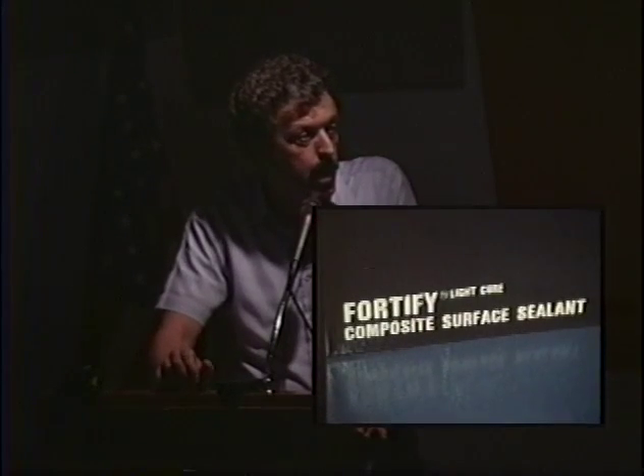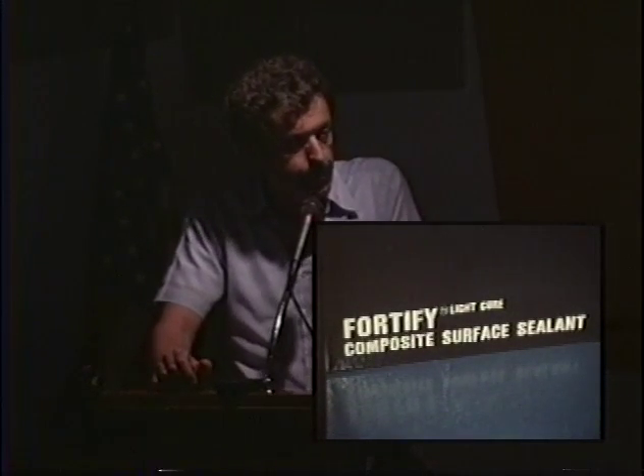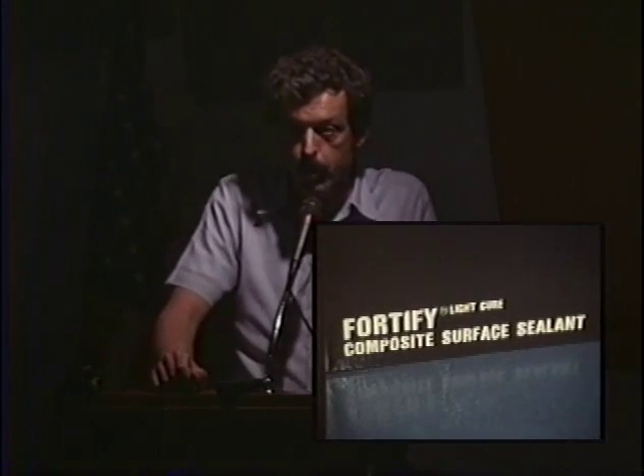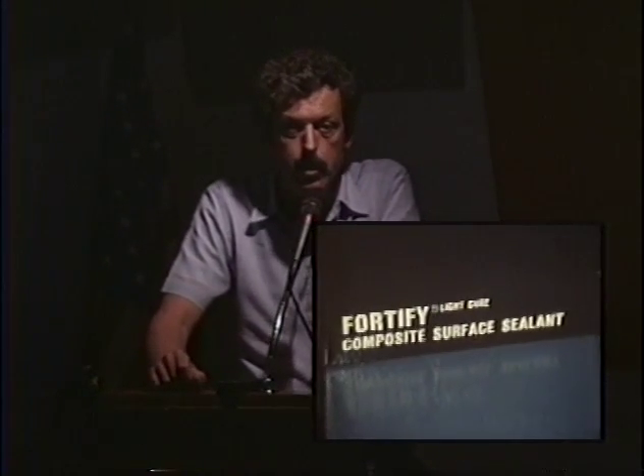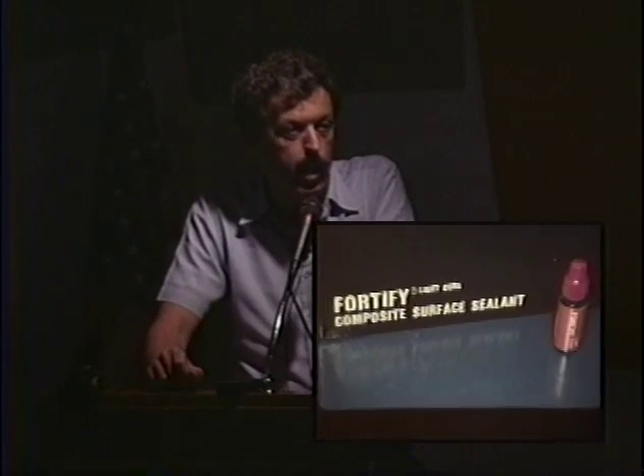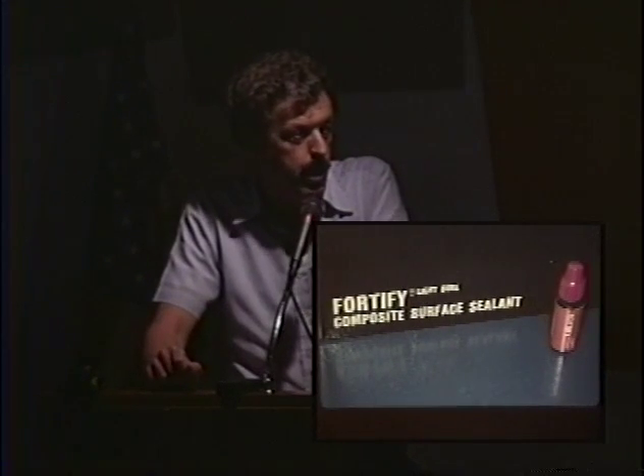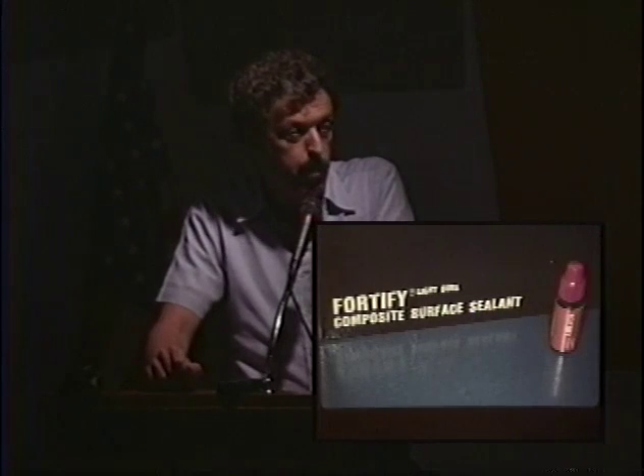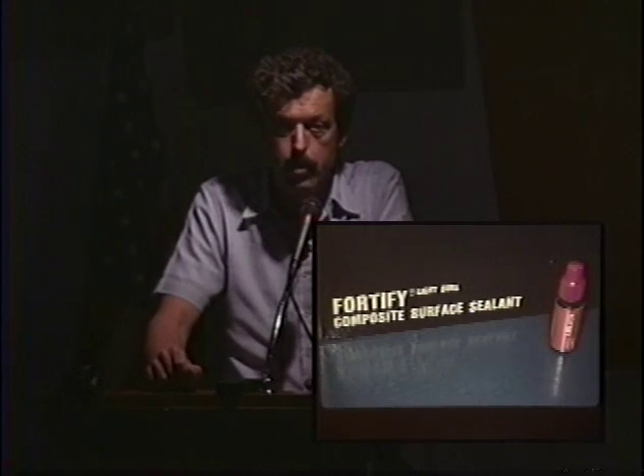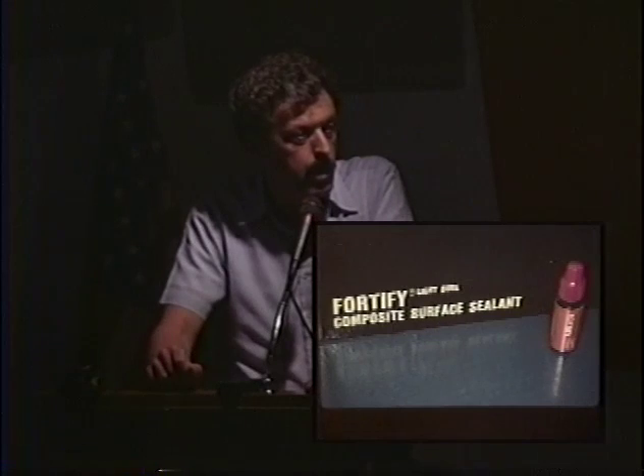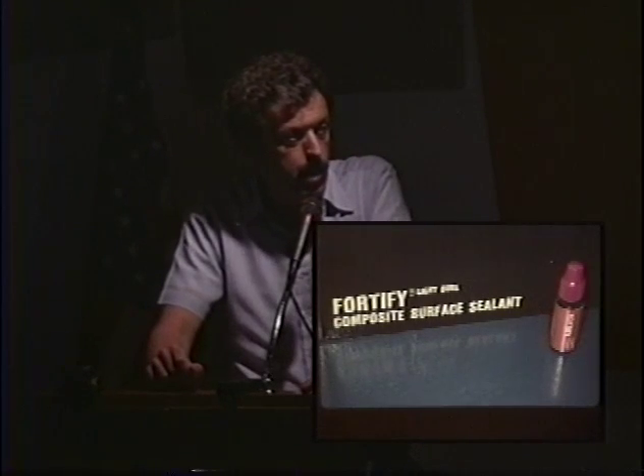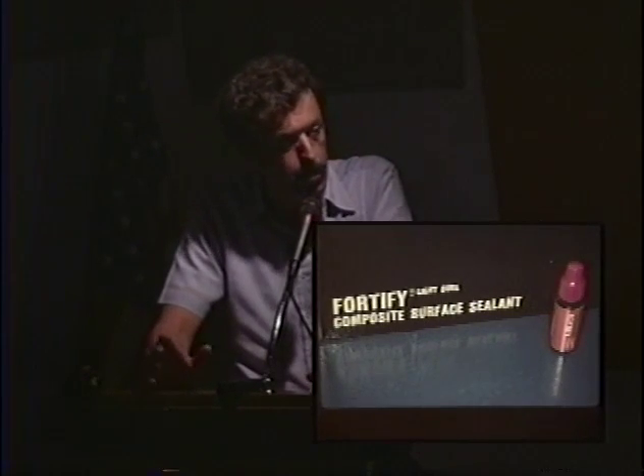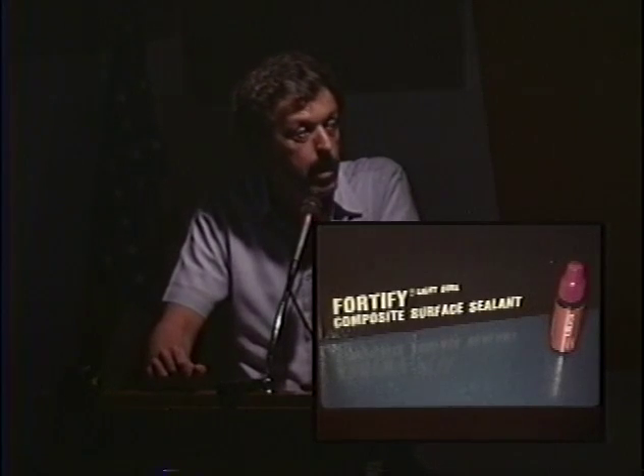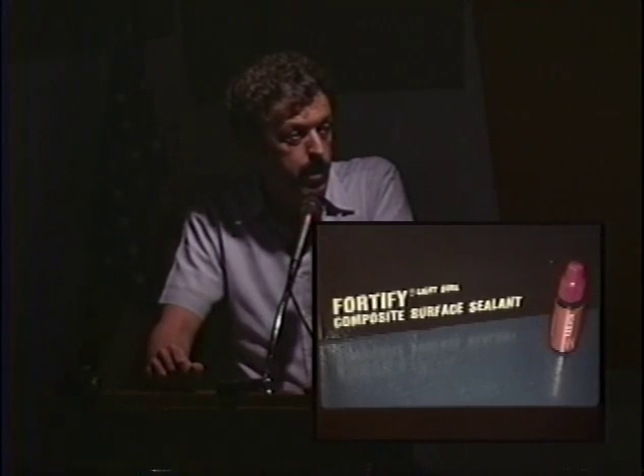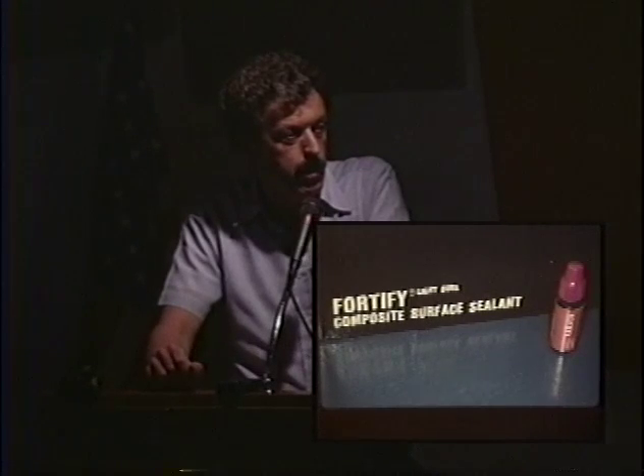The product that'll do that the best is called Fortified by Bisco. That material there is capable of penetrating a very small mystery defect, one we don't quite understand. Now, if you use occlusal sealants, they're too high in viscosity and they don't seem to do much good in that regard. So this is a unique product so far as I know. The basis of the chemistry is urethane dimethacrylate, which is, of course, a low viscosity diluting monomer, usually put in other composites to thin them down a little bit. And you put it on there, and it just gives a hell of a difference in the result.